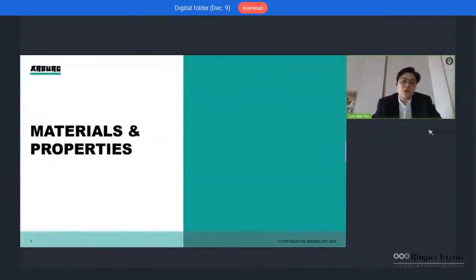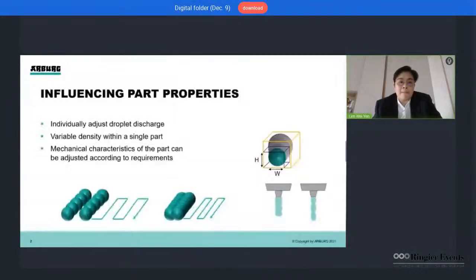Let me go a little bit deeper into materials and properties. The most interesting feature of the plastic free-forming system is the nozzle closure system, which makes it possible to handle thermoplastic materials with very different properties. The process even works with materials that have very low viscosity, as long as the melt pressure is high enough to open the nozzle.